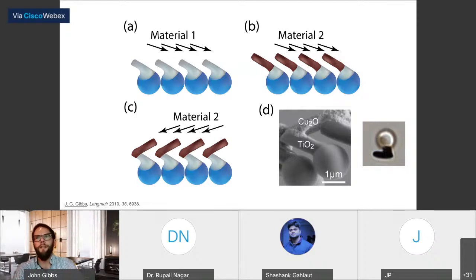And we made them into these sort of jagged, V-shaped structures in order to be able to analyze their movement better. So when we switch between the different fluorescent sources, hopefully we'll be able to know, if you look at the microscope image down here on the right side, that next to the sphere, that's the TiO2, and the one that is at a little bit less than 90 degrees, so it's probably like 75 degrees or so, is the copper oxide. So by using that morphology, we could at least tune in or see what was happening when we had different light sources and how that corresponds to the material that they're made from.